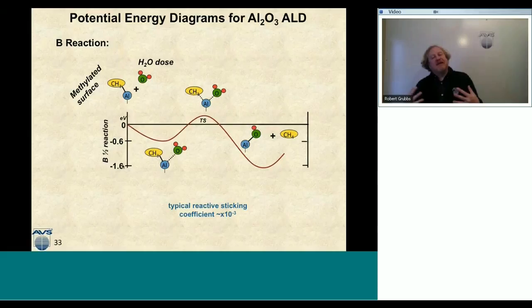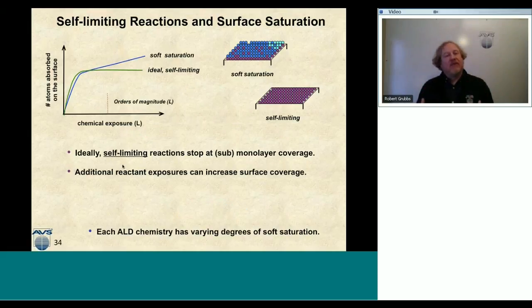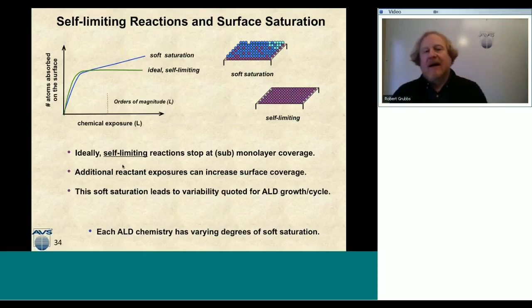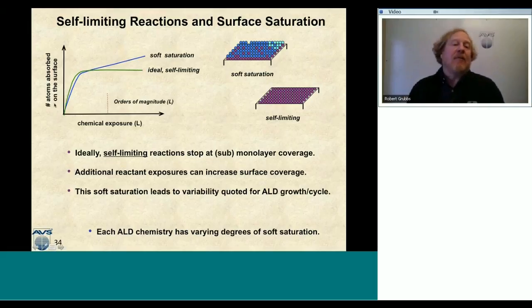Now, I mentioned that we reach this self-limiting behavior of these reactions, and sometimes there's an ideal self-limiting, and sometimes there's something called soft saturation. So on this plot to the left, I have the number of atoms absorbed on the surface as a function of chemical exposure in L, given in Langmuirs. And so as I add chemicals to the surface, they all get absorbed onto the surface. And then in an ideal world in ALD, the more chemical precursor I add to the surface, I don't necessarily add any more atoms to the surface, which is given by this green line right here. So this would be the ideal self-limiting behavior of atomic layer deposition.